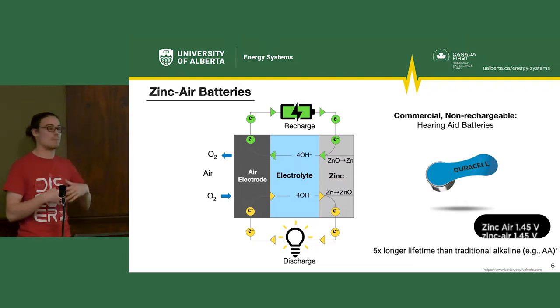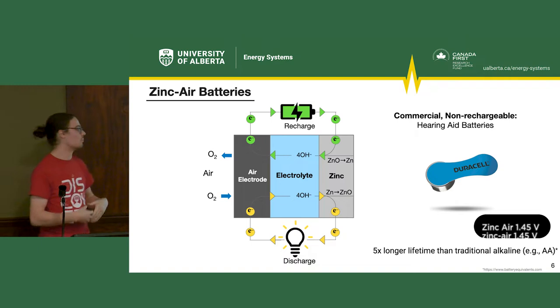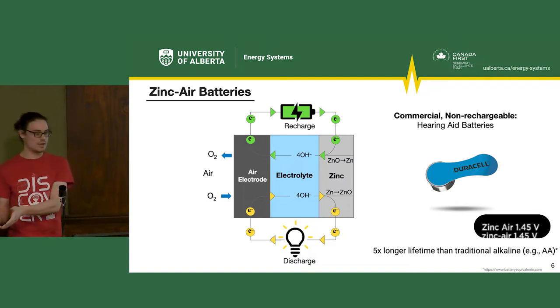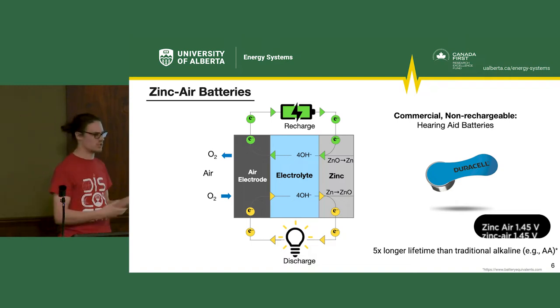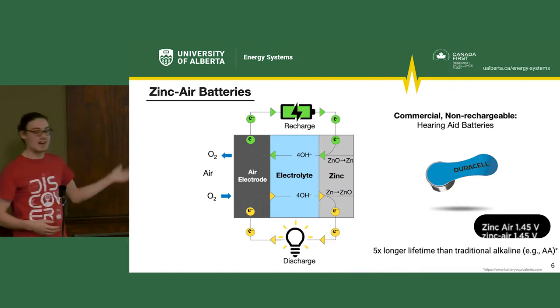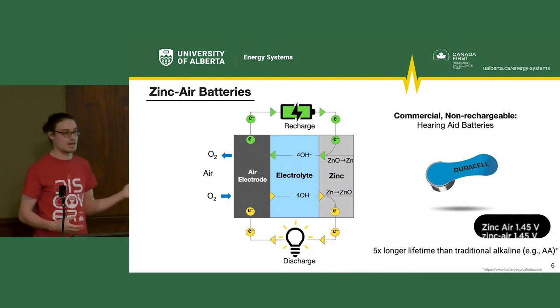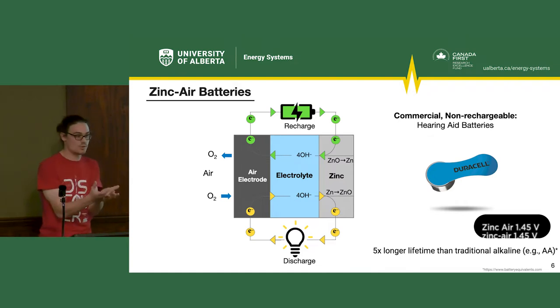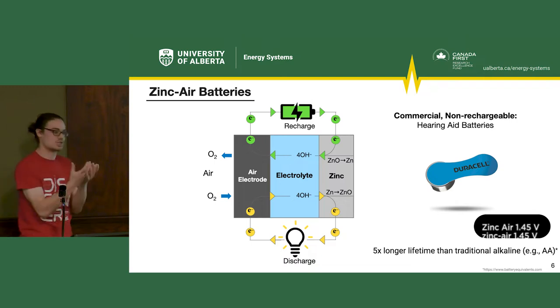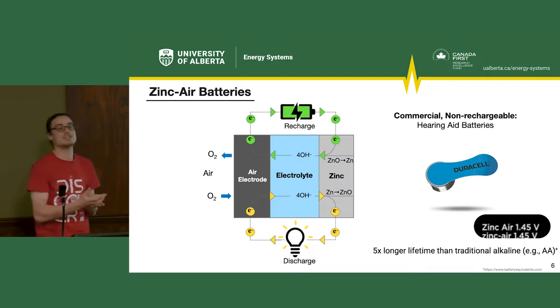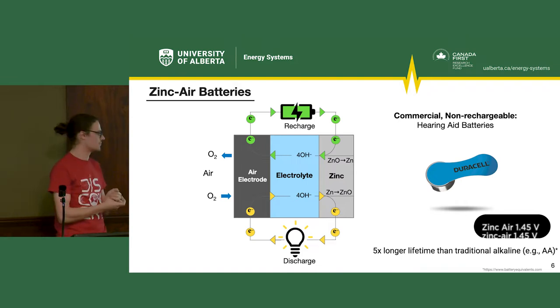And as a result, we don't get a lot of power out of the battery right now, but the power is enough for a hearing aid. And if we're using a zinc air versus, say, a AA battery, we get almost 5 times more lifetime out of a single battery because we're not storing that air, right? The air just comes in. So we're just storing the zinc. So we get more energy density, as it's known, from a zinc air battery versus other battery chemistries.